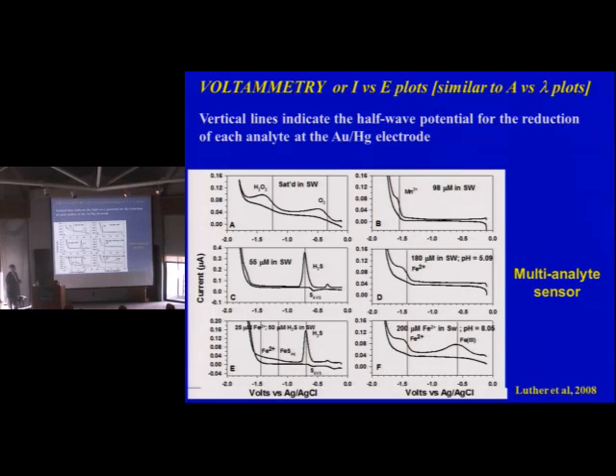You actually get a peak for iron 3. And these are iron 3 nanoparticles, usually stabilized by organics that are natural in the solution. Okay? So we don't have standards, unfortunately, for iron 3. But before I go any further, the detection limits are approximately 3 micromolar for oxygen, 5 for manganese, 10 for